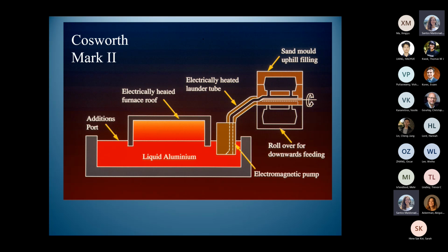I'd say that from the day this machine came into being, actually the Mark I machine to be truthful, but this is similar, no engine ever failed again. So we came from 50% failures on the test bed to 0 overnight. So the whole business of fatigue and being able to control fatigue, I see as being primarily a casting problem. It's the way we treat the liquid metal which controls whether it is or isn't going to fail by fatigue.